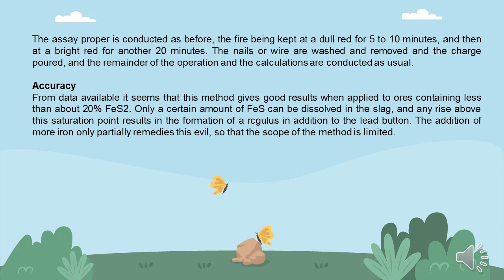Accuracy. From data available, it seems that the method gives good results when applied to ores containing less than about 20% FeS2. Only a certain amount of FeS can be dissolved in the slag, and any rise above the saturation point results in the formation of a regulus in addition to the lead button. The addition of more iron only partially remedies this evil, so that the scope of the method is limited.